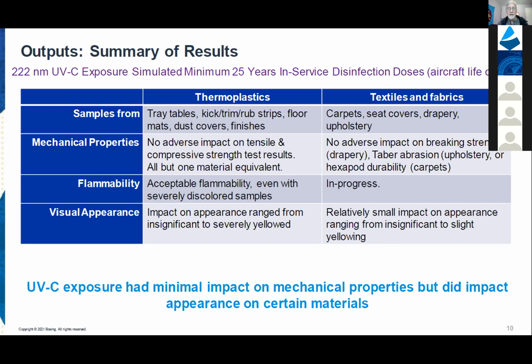Now for visual, we saw a range of results. Everything from hardly any change where you couldn't tell to something that had gone from bright white to severely yellow, almost brown. And then flammability was my biggest concern because, as you know, in the additive industry, you add these, and they're going to be throughout the sample. And I worried about oxidative degradation and the impact of oxidative degradation on additives that are at the surface. How would that affect something like vertical Bunsen burner on a sample that normally would easily pass?